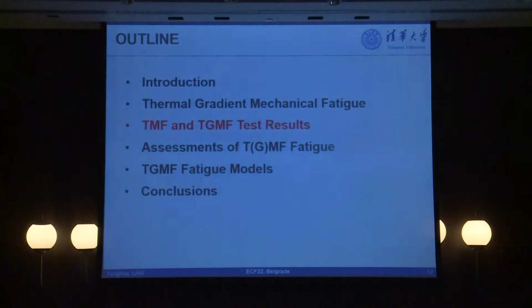So what I mean is, we are going to talk about both thermomechanical fatigue and thermal gradient mechanical fatigue, both cases. What we obtained, what you see here, is the TMF result. That is all the result in the in-phase case. And the red value was obtained by an Indian colleague. He published the work here, and that is from NASA. In that sense, we effectively use rather different materials. All of us use Inconel 718, the most popular nickel-based alloy in aero engines, but the manufacturers are different. Therefore, we cannot guarantee it was the same material.